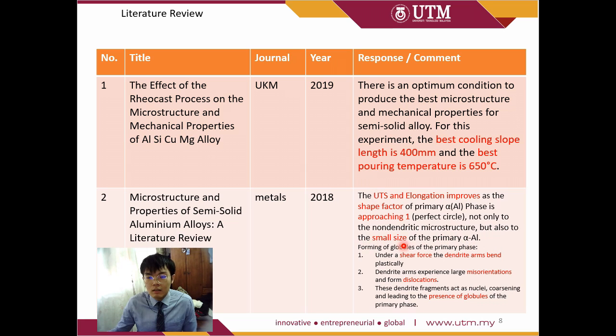This is the mechanism of the forming of globules. Under a shear force, the dendrite arms bend plastically, and the dendrite arms experience large misorientation and form dislocations. These dendrite fragments act as nuclei, leading to the presence of globules of the primary phase.